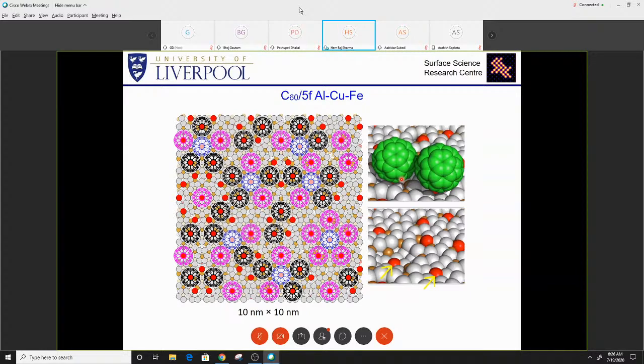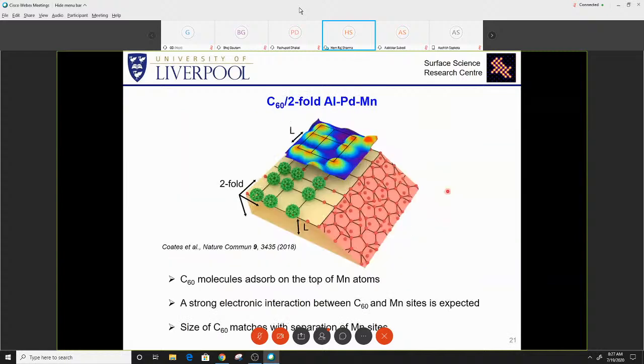So, so far I showed you all examples of quasicrystalline structure, but with 5-fold and 10-fold structure. But 2 years ago, we demonstrated for the first time that there might be a physical system with quasicrystalline structure but with 4 folds. This happens again when you deposit C60 on another type of surface, a 2-fold element. So here you see when you deposit C60 on the 5-fold surface, this picture basically shows distribution of magnetization where you see C60 on 2 different surfaces, the 5-fold one, which is interesting, and the 2-fold one.